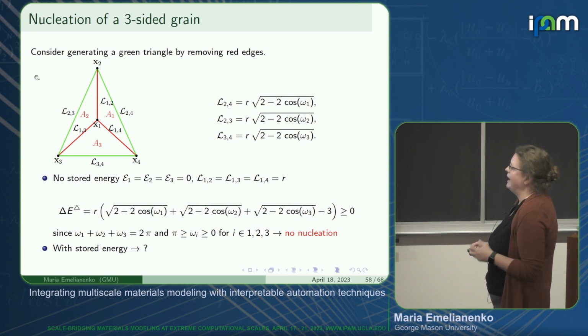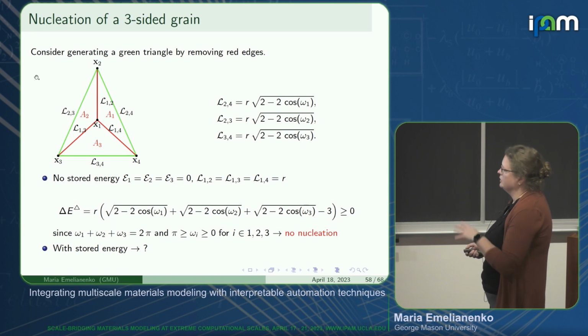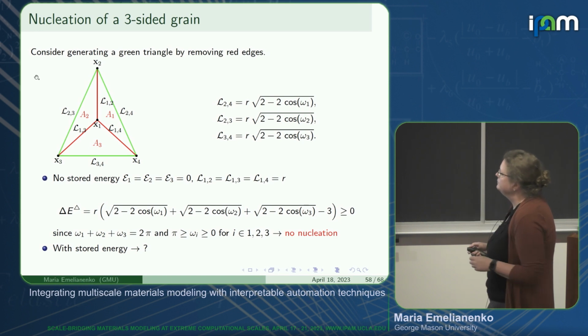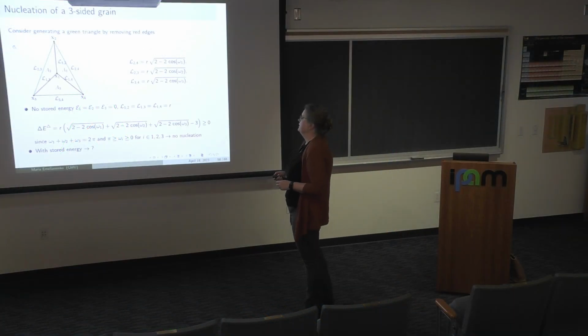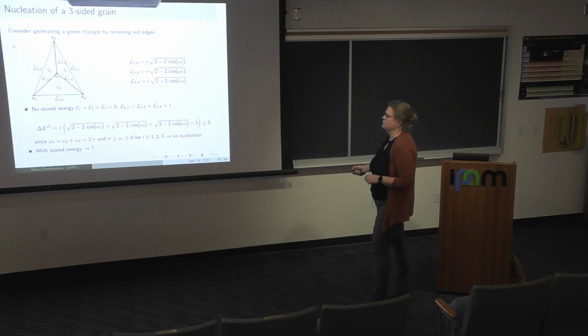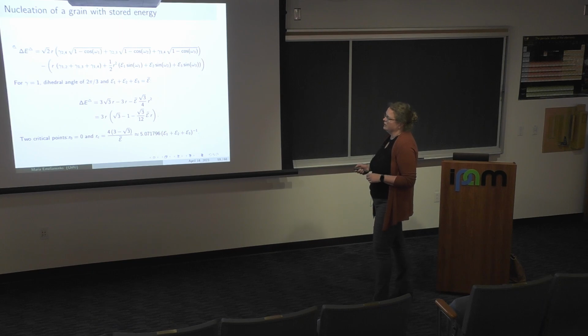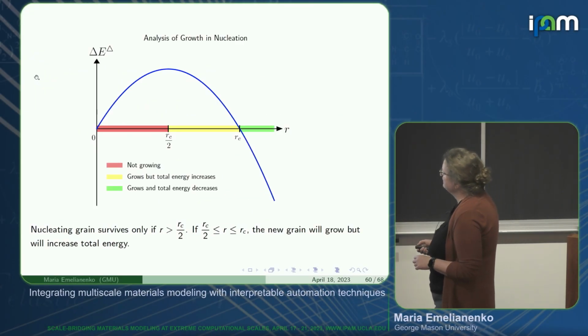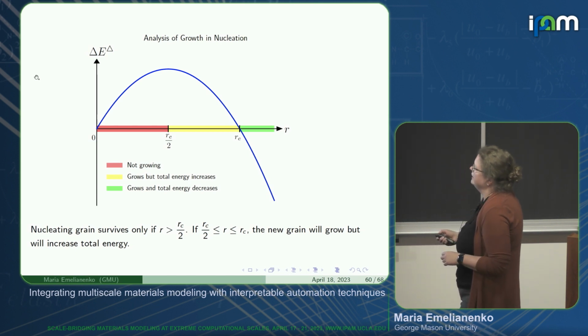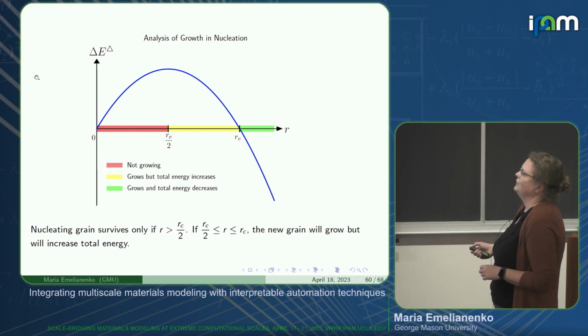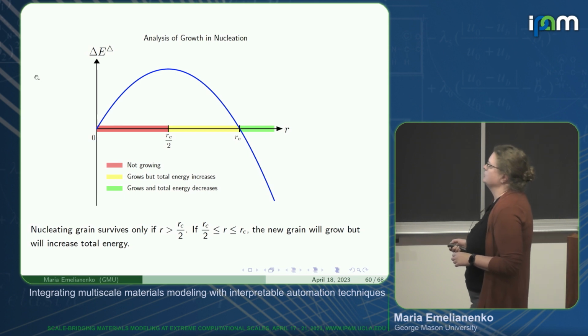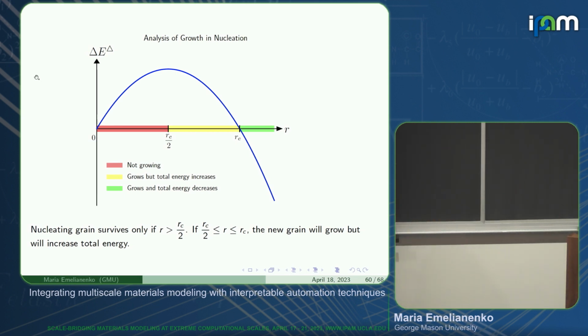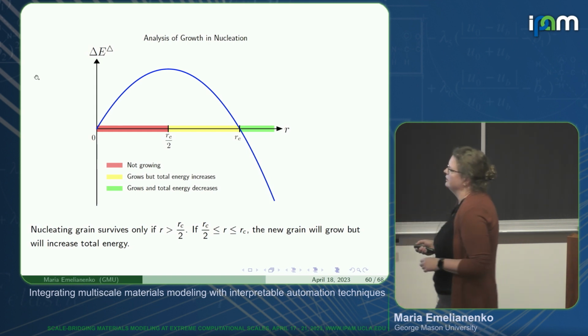This is a little bit more detail about how to nucleate. So we basically look at the middle of the triangle, and we nucleate a grain if a certain condition holds. That's based on the stability principles that we defined, and we have the critical radius of the grain derived, for which we can expect nucleation. And here is a picture showing that if you exceed a certain critical radius, then you definitely nucleate. In this regime, the grains will grow, but the total energy will increase, and then you do not have a growth in the red area.